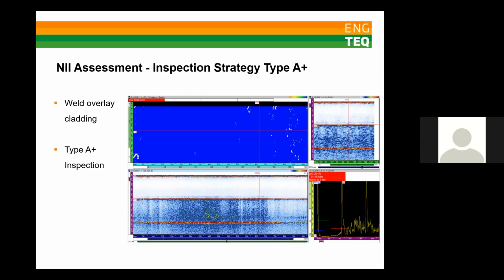So this is the most likely scenario, and this is the current focus for NII carried out in clad vessels. The scenario would potentially lead to high corrosion rates in the carbon steel base material, following failure of the corrosion-resistant alloy cladding. So the purpose of a type A plus inspection is still to confirm the absence of degradation, but due to the difficulties associated with detecting low-level degradation, a significantly higher coverage is required.